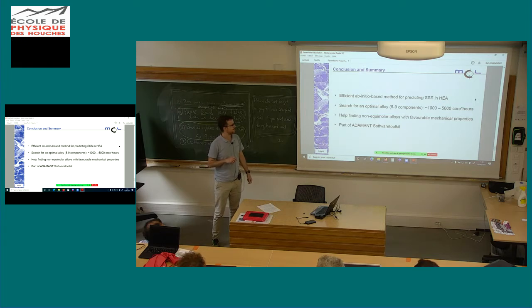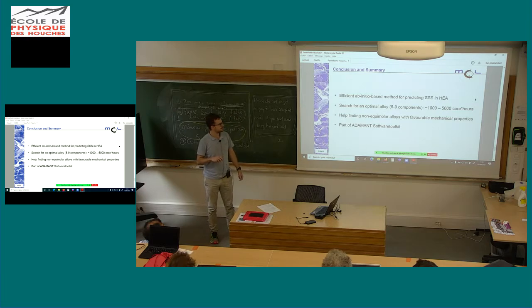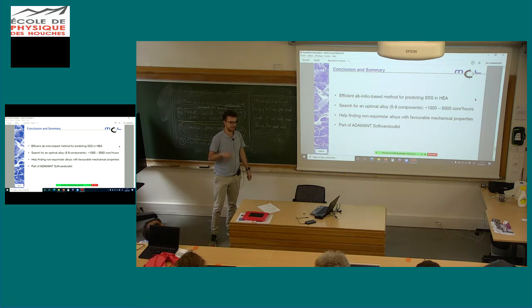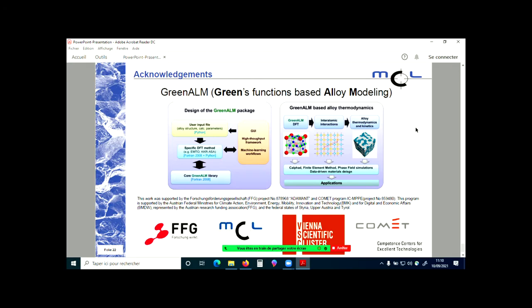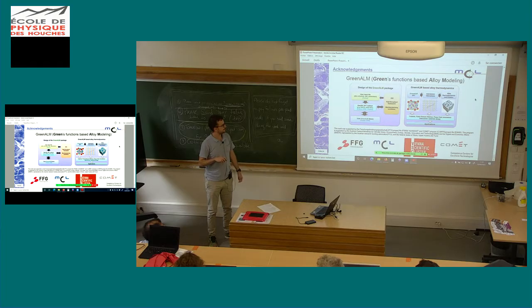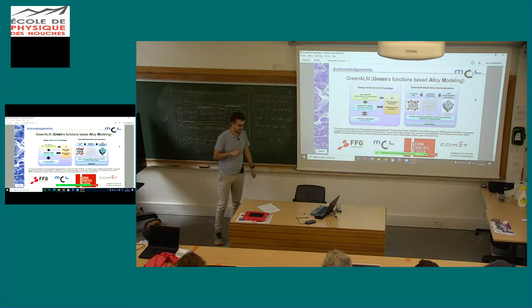Yeah. So to conclude, we made an efficient ab initio-based method for predicting the solid solution strengthening in now multi-component alloys. I called it here now high entropy alloys. It's quite efficient. It takes not really a lot of core hours, so you can even run it on your workstation. It helps finding non-equimolar alloys with favorable mechanical properties, and it's part of the ADAMANT software toolkit, which is effectively some kind of toolkit that helps you modeling dislocations and mechanical properties. And finally, I also want to advertise that we are developing Green's function codes, and I want to thank my funding agencies, which basically keep me employed. Okay, thanks a lot.